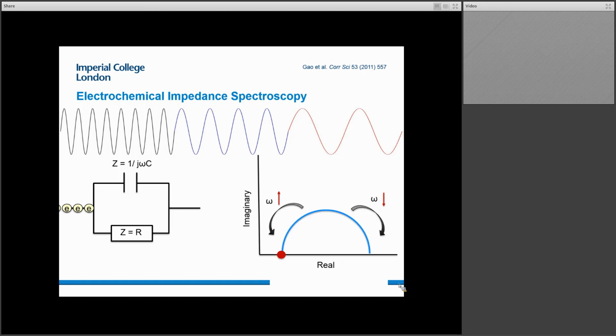What we find at very high frequencies, that's the black sinusoidal lines, and if you look at the red dot on the figure on your right, is that our electrons preferentially move towards our capacitor under these conditions. As that frequency becomes very high, the impedance is effectively zero. But of course, this is only one extreme, and we're going to move our frequency lower.